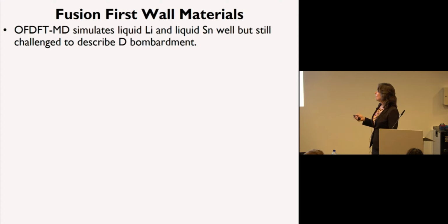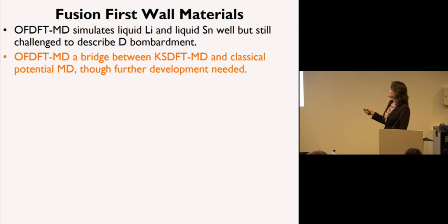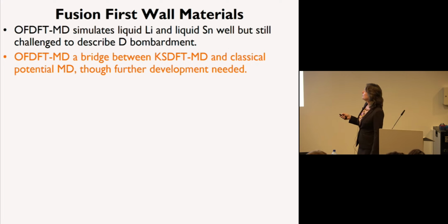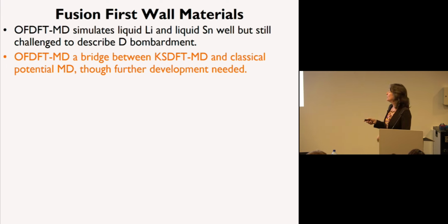So just to summarize this piece of the talk, what I have shown you is that orbital-free density functional theory can do very well at describing these pure liquid metals. We still have lots of room for new contributions to figure out kinetic energy functionals that can describe both localized densities as well as delocalized densities. So we can't really describe the deuterium bombardment yet. Classical potential MD is still much faster than orbital-free DFT MD, but orbital-free DFT MD is much faster than Kohn-Sham DFT MD. And so from that point of view, you can think of it as this intermediate simulation method.